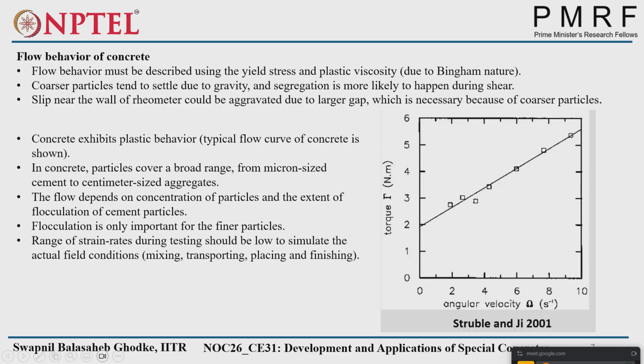Because in concrete a wide range of particle sizes are used, we observe a more complex nature of behavior. So flow depends on the concentration of particles and the extent of flocculation of cement particles, and flocculation is only important in the case of cementitious particles. It will not happen in inert particles, such as the fine aggregate or coarse aggregate.